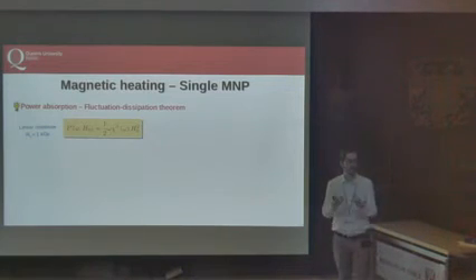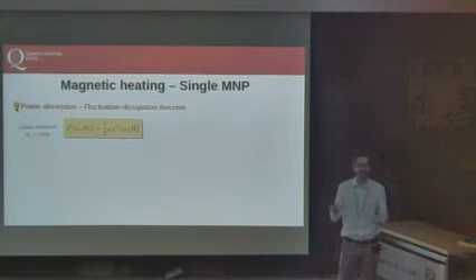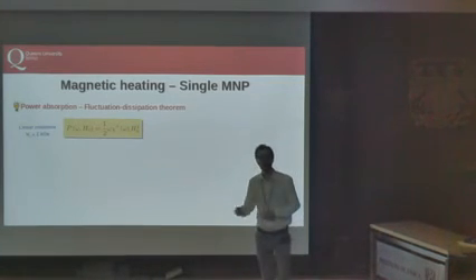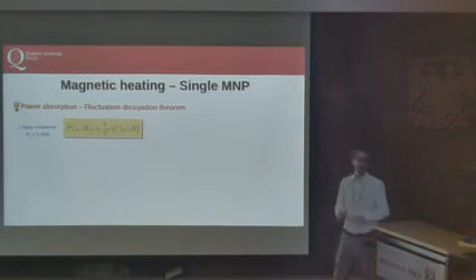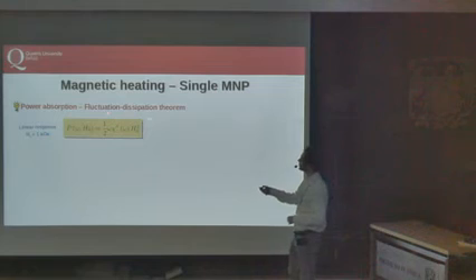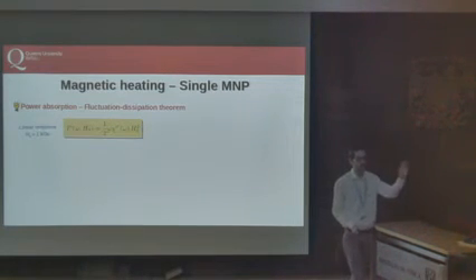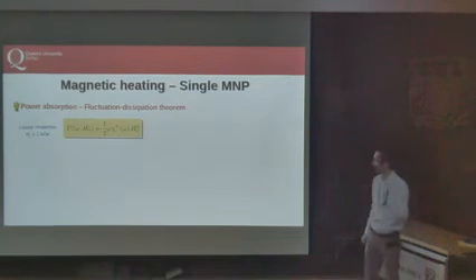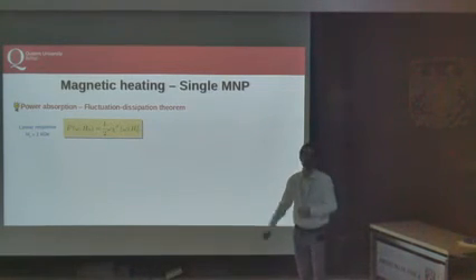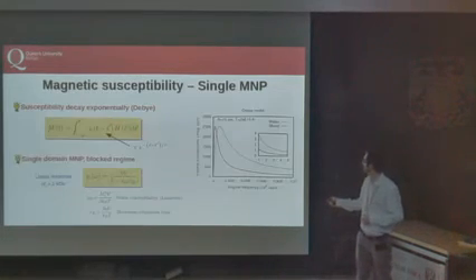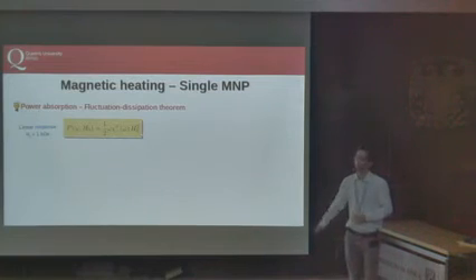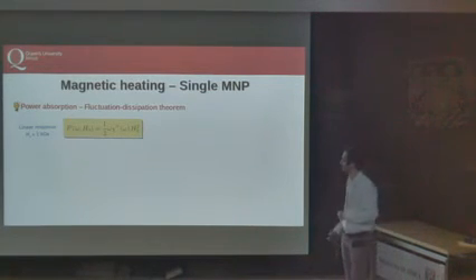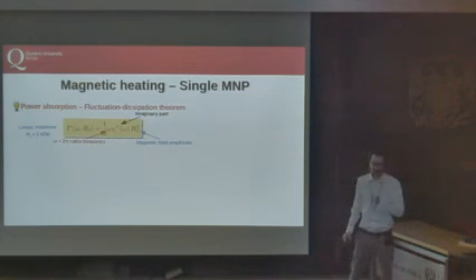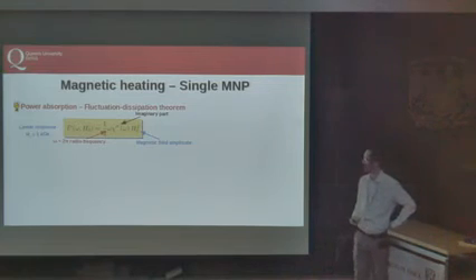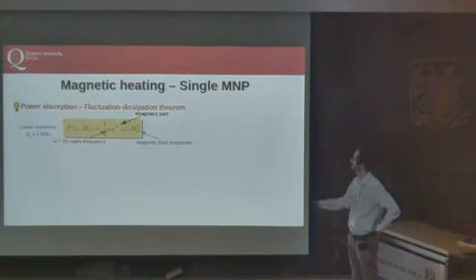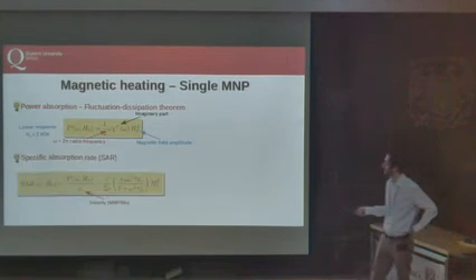How does the SAR, which is a quantity which with certain uncertainty we can measure in experiments, how is the SAR related to the susceptibility? Well, for small field, this is done through the fluctuation dissipation theorem. So the power absorption for a given amplitude of field, H naught, and a given angular frequency, is given by 1/2 the frequency, the imaginary part of the susceptibility, this one, and then the square of the amplitude. As I said before, the frequency here is 2 pi times the radio frequency that I provide in kilohertz. This is the imaginary part, this chi double prime, and this is the square of the magnetic amplitude.